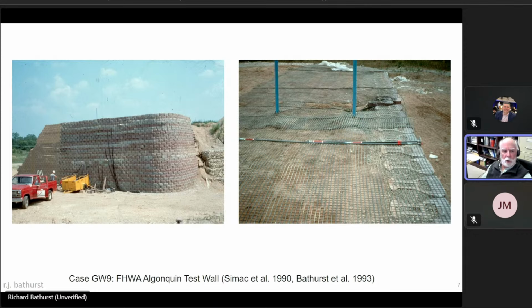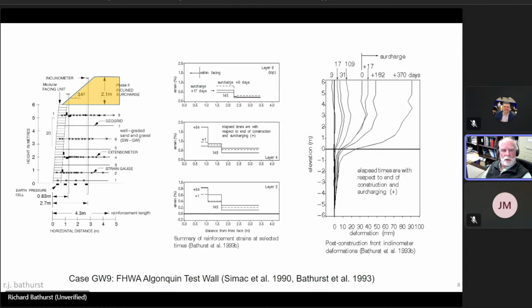So here you can see a modular block wall, and the right-hand side shows it during construction where a reinforcement layer is in place. You can see some extensometers, and you can see some slope inclinometer casings as well. And from these types of tests, we could gather useful information. So you see a cross section on the left-hand side of the wall. You can see that there's a lot of instrumentation, including strain gauges. And in the middle of the slide, you can see some of the strain distributions that were recorded in this wall during construction and during surcharging. And on the right-hand side, you can see wall deformations, for example. So there were some quality measurements from full-scale walls that were available.